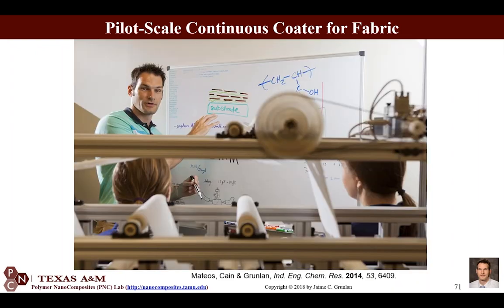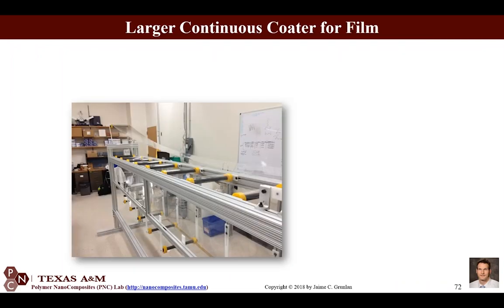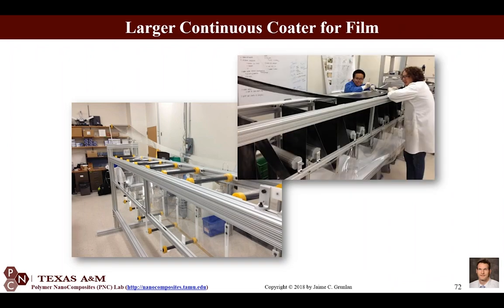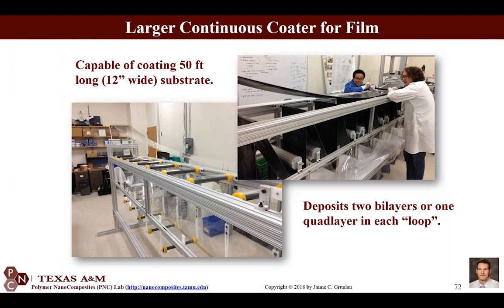This is cotton fabric on my little pilot coater, and then we built a bigger pilot coater that's a 50-foot, 12-inch wide coater, and we coated thick rubber, thin PET film, fabric. We've done a number of things, and it works very smoothly.